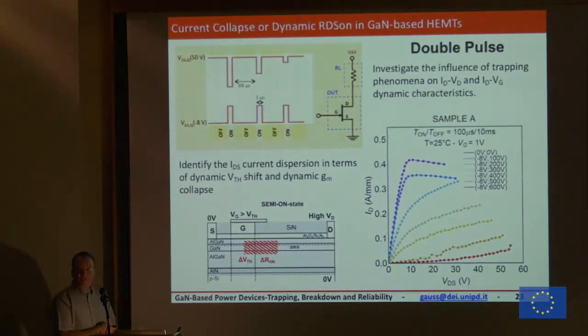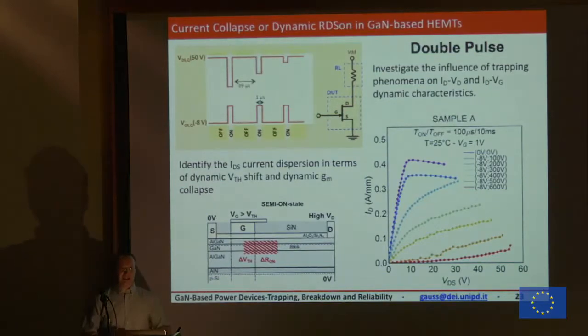In the next step, this was called dynamic RDS-on, in the sense that RDS-on is the slope of these curves, okay? But dynamically, if I measure in a pulsed condition, I can see this one. So this is the static, this is the dynamic. And you see the large increase. And remember the first speech of Peter. He spoke about how we need to reduce as much as possible the on resistance to have much less dissipation. We are going exactly in the opposite direction.